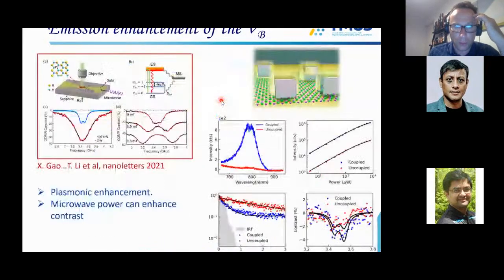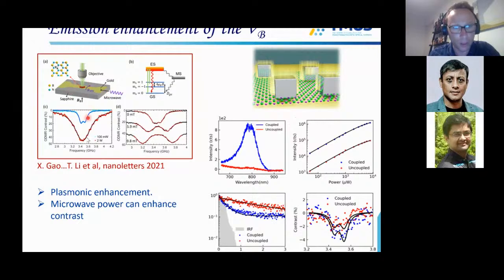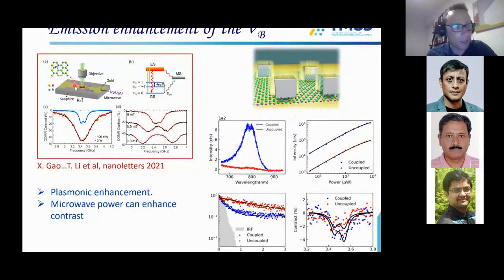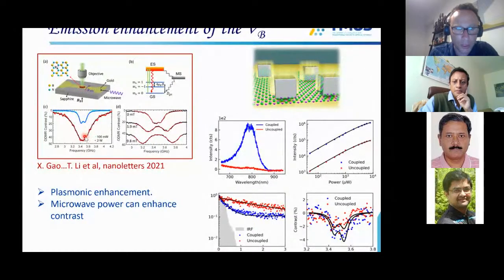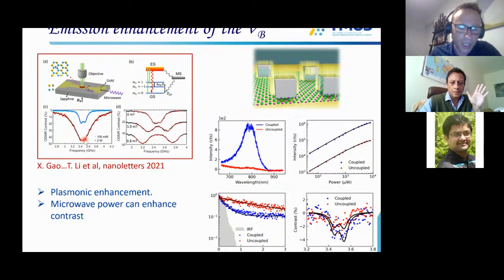And so, of course, this was quite an interesting system, and other people are already doing quite nice work with it. So this is the work from Tong Li's group at Purdue, and they actually improved the contrast significantly. If you put this hBN on top of your microwave strip to generate the microwave, you can get up to 50% contrast. Remember that, for example, in NV in diamond, the contrast is only about 10-15%. Now we're reaching 50% contrast, with the magnetic field resolved, so that's quite cool.